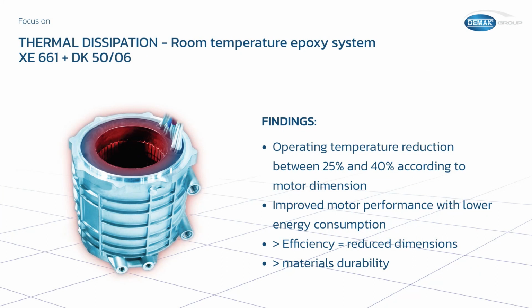Another interesting system, used also for motors, also with room temperature curing, is the XE 661 and the DK 50/06. In this case, the TG is lower. We speak about 65, 70 degrees. But tests performed on motors show that operating temperature is reduced between 25 to 40% according to the motor dimension. It means a lot more life for the motor in working, in exercise.